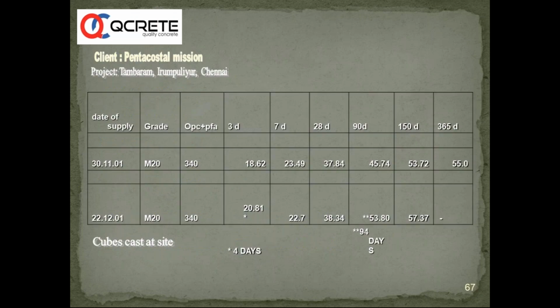So this was a Pentecostal church in Chennai long back, and here it is a classical case where we cast the cubes on site actually, and you can see a 240 plus 100 kg mix, 240 OPC, 100 kg fly ash. We had a 28 day strength of about 37-38 MPa, and in 365 days it jumped from 38 to 55, which is the fly ash from Ennore thermal power plant, class F fly ash. Again, another case where we had this 28 day strength of about 38.34 and 150 days about 57 actually.